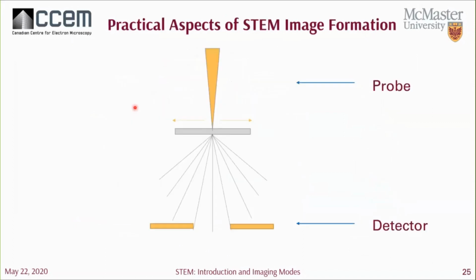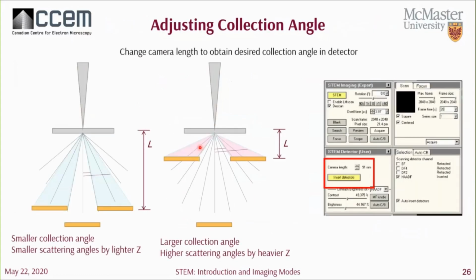All right, so that was a brief discussion of forming a really nice probe. Obviously, there's a lot more that goes into it, but now we can go into the detector. Once you form a nice probe, you'll need to adjust your detector so that you're collecting at the right angle. You want to collect these electrons that were scattered to a high angle. You do that by changing the camera length, i.e. you are just changing the distance between the detector and your sample.